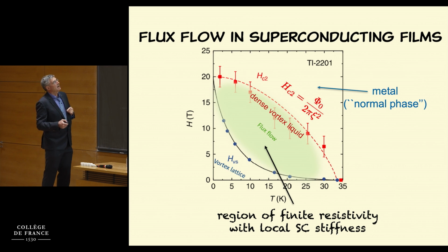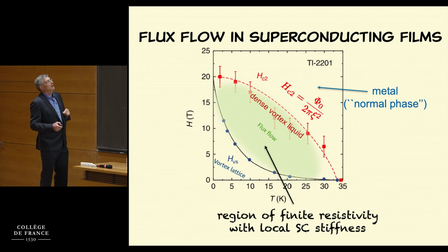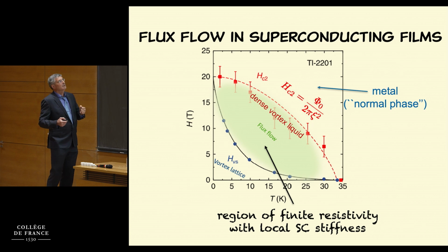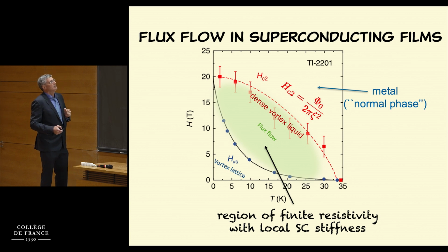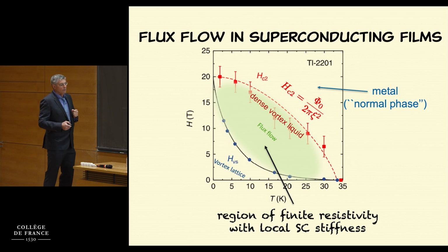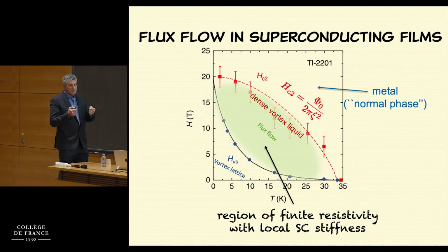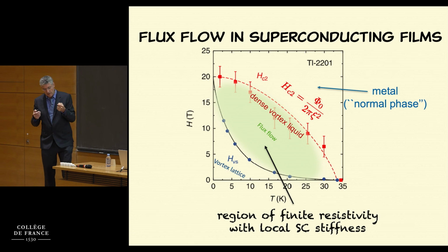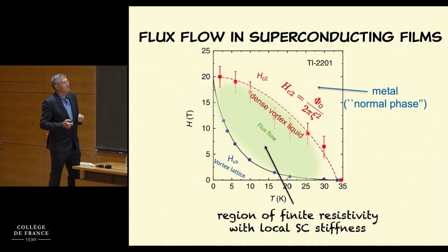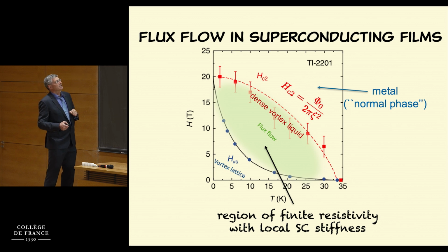Usually people put some kind of a line between them. It's very difficult to determine that line in many cases because it's a crossover where the vortices touch each other, and they call it HC2. But what is interesting is that in this flux flow regime, one really has to consider the fact that the vortices feel each other. At short range, there's rigidity, and they repel each other quite strongly, and that's not a property of metals. So there is a difference in the transport.